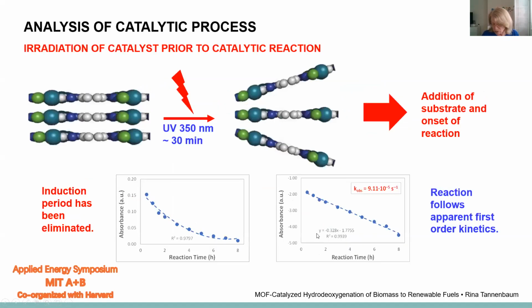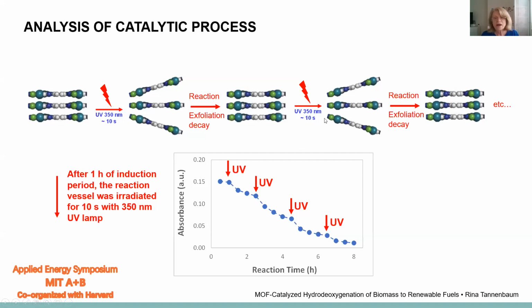So each time we open the sheets, we help the sheets. So we help the reaction along by helping push the reactant and the solvent through the layers, by helping open the layer, by exfoliating the 2D layers and exposing the reactive sites to the reaction.